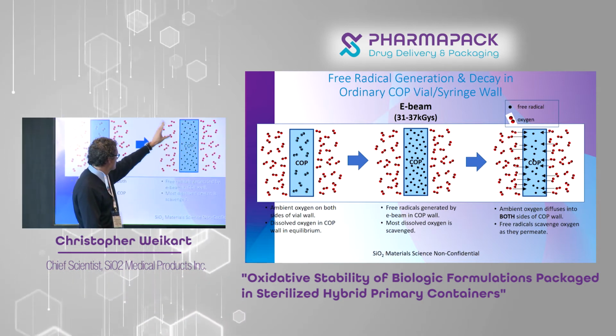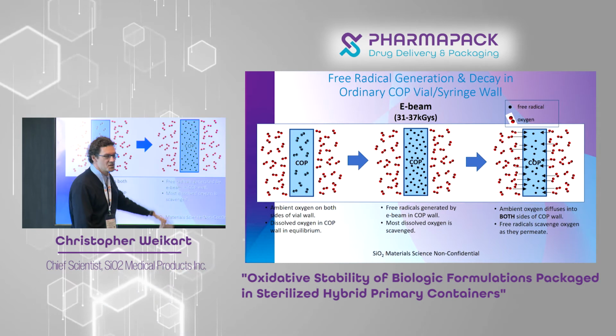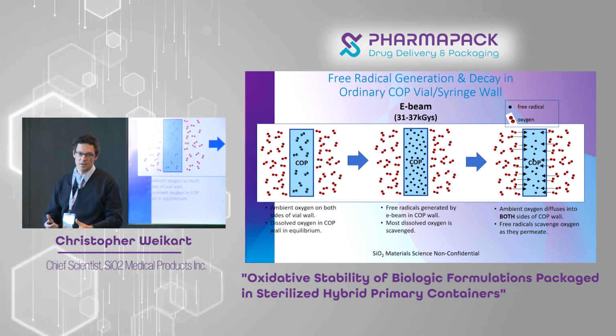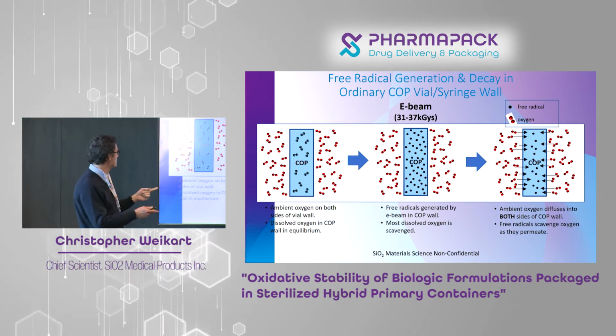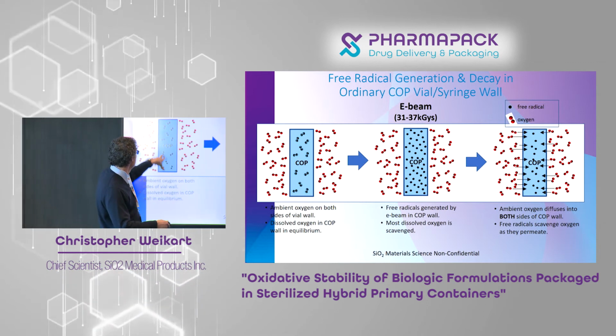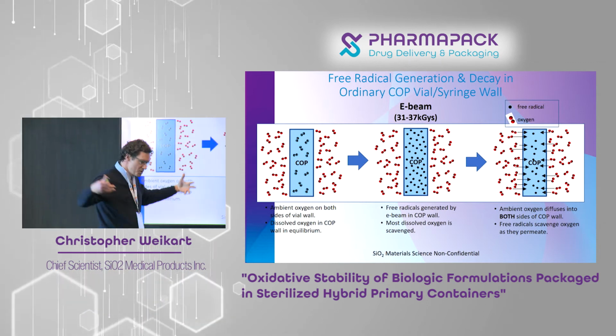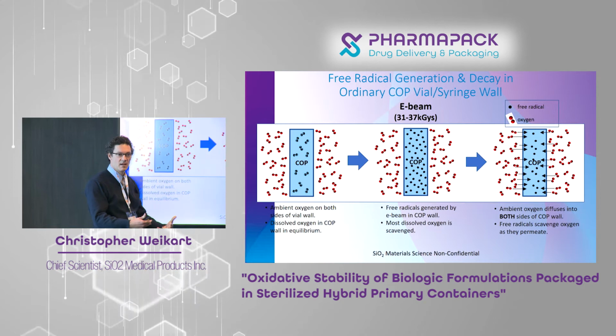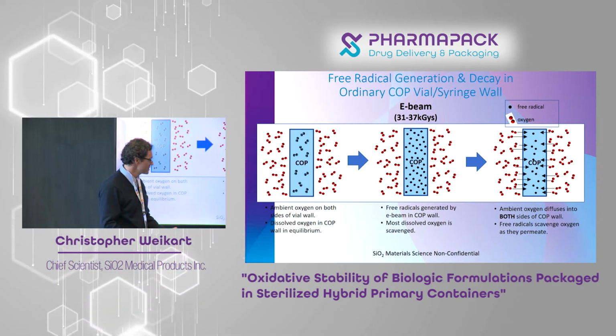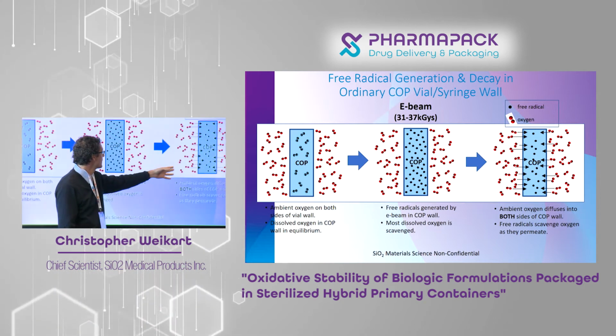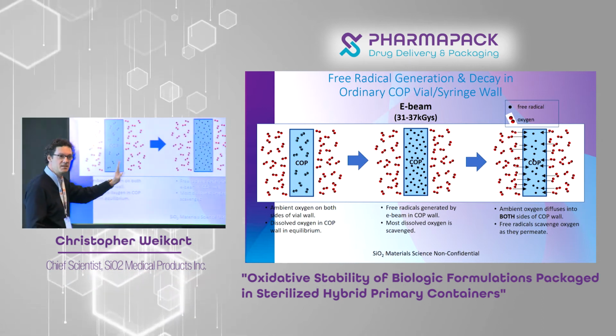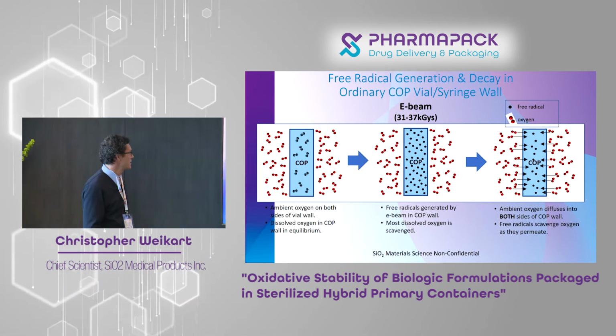But you hit it with gamma, and you form what's called free radicals in the polymer. Okay? And what ends up happening is the free radicals end up getting scavenged by oxygen in the polymer. And then, of course, you get oxygen diffusing in and scavenging those free radicals. And you can see that happening over here. Okay, this is for an ordinary, plain, uncoated COP container.